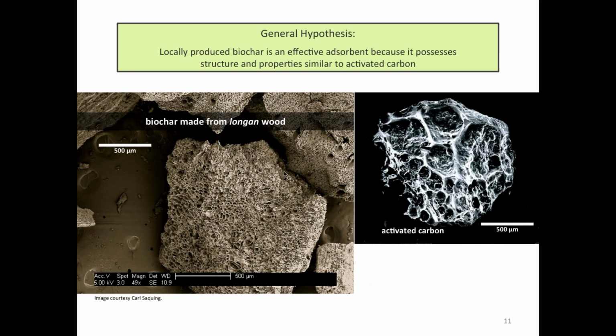So here I'm showing electron microscope images of a piece of longan charcoal, or longan biochar, and you can see at this scale these grains, which are each about 1 millimeter across, have a bunch of macro-sized pores in them. And if you go into those pores, you'll find yet smaller pores, and if you go into those pores, you'll find yet smaller pores, all the way down to the nanometer scale. And it's that internal porosity that provides a lot of surface area. In the case of a good water filter biochar, you're talking about, say, 500 square meters per gram of material. So a tablespoon of material could have 500 square meters, or something like the size of a soccer field, of surface area internally. Microporosity is pretty much the key to getting a good adsorbent material.